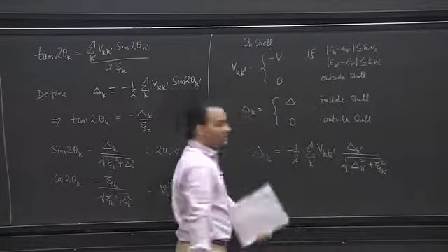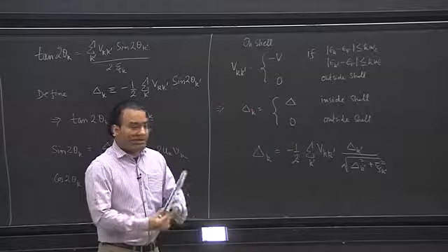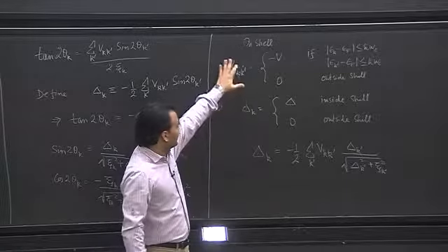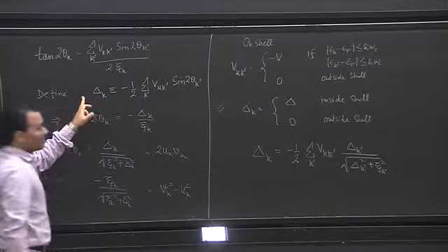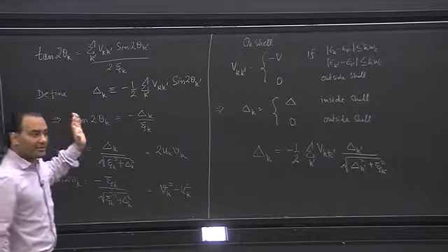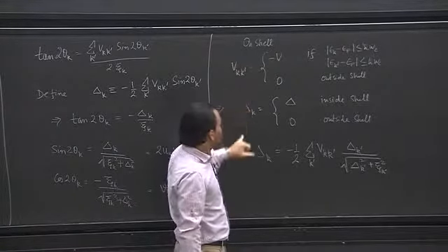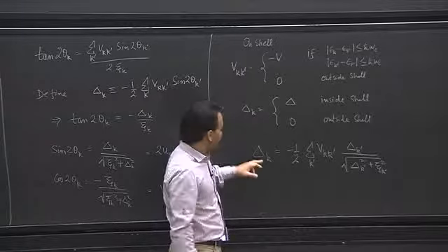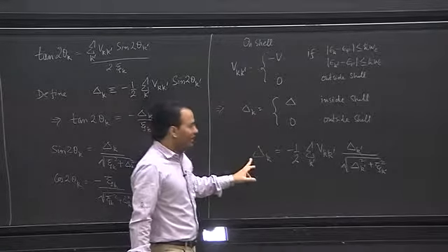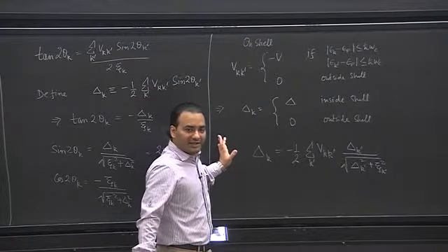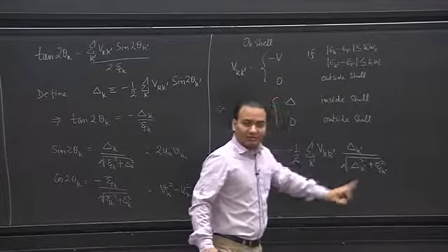Now in this equation, if we put delta k to be a constant, within this approximation, this is the equation that we obtained by minimizing the Hamiltonian, and now within the on-shell approximation we know that delta should be a constant. If you put delta to be constant here and here, you'll see one factor of delta will just cancel out, and you'll be left with just this one.